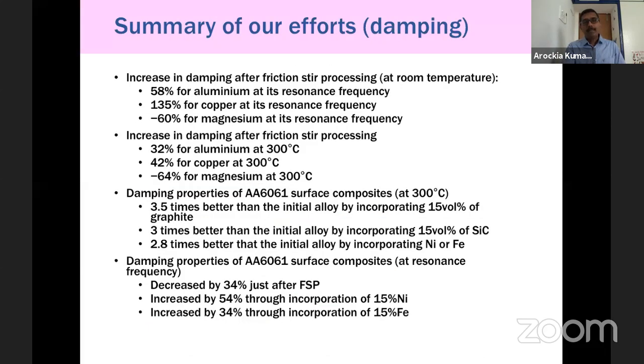So the summary is, I don't want to go step by step. The damping property is greatly enhanced after FSP, and also by incorporating silicon carbide particles or iron or boron nitride or nickel. So we have effectively used FSP to alter the damping properties of the material, in addition to improving the mechanical property, and that's the key message here.